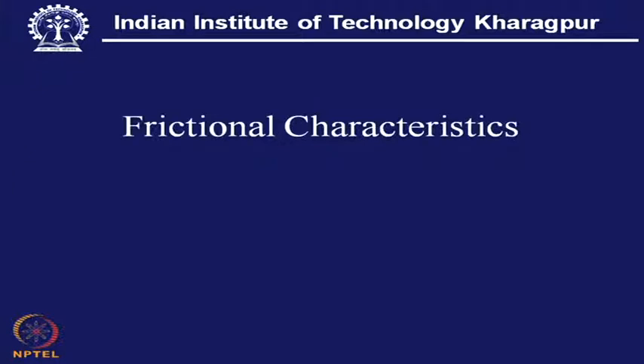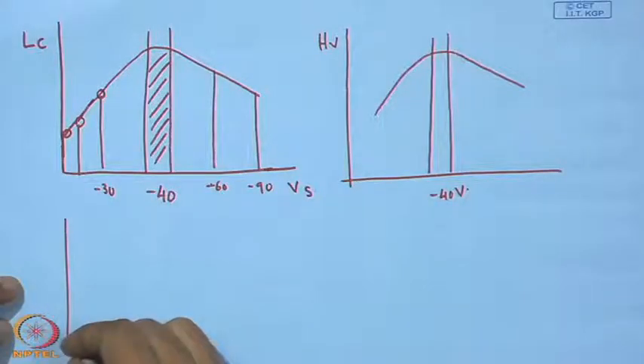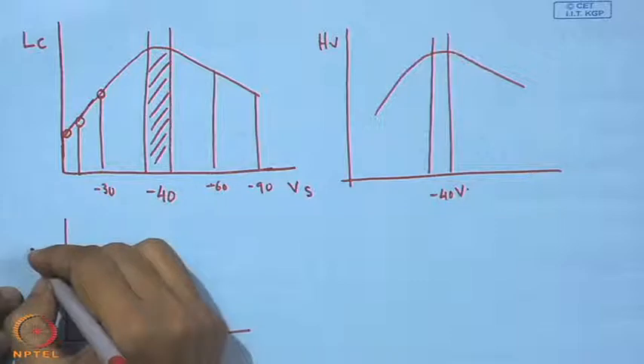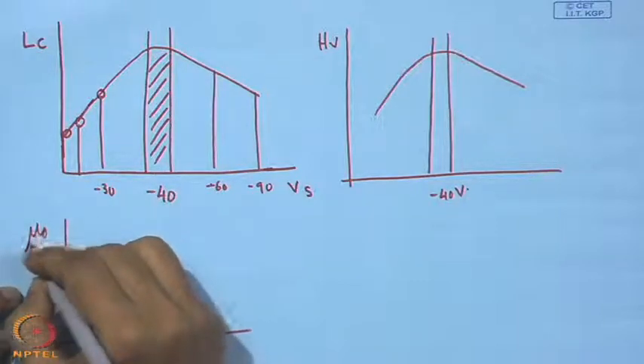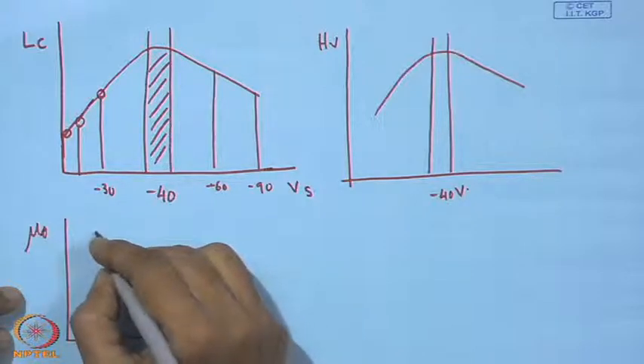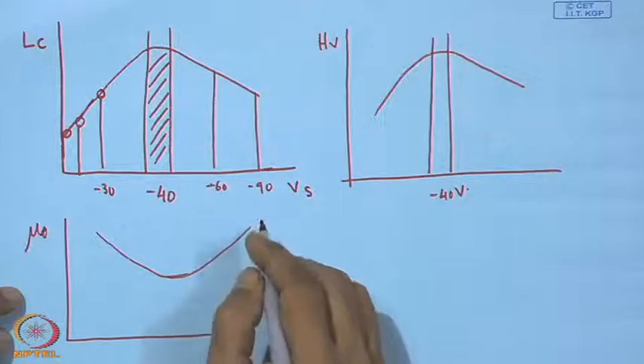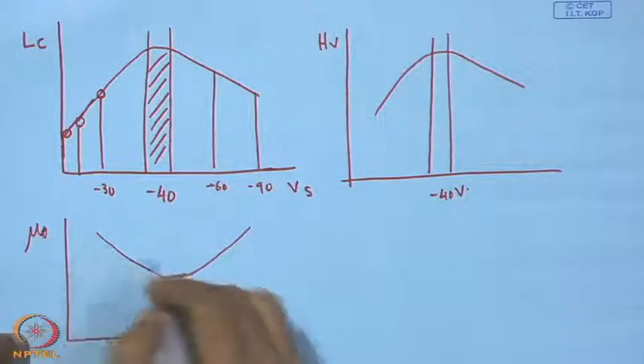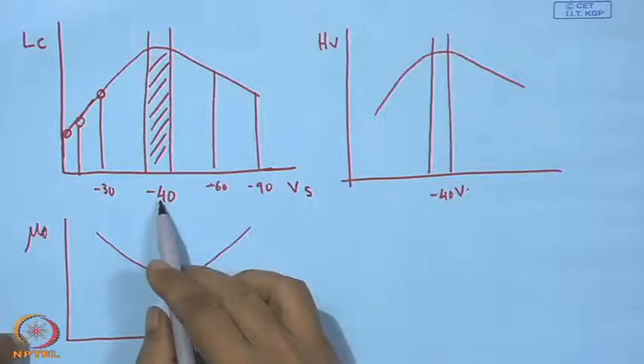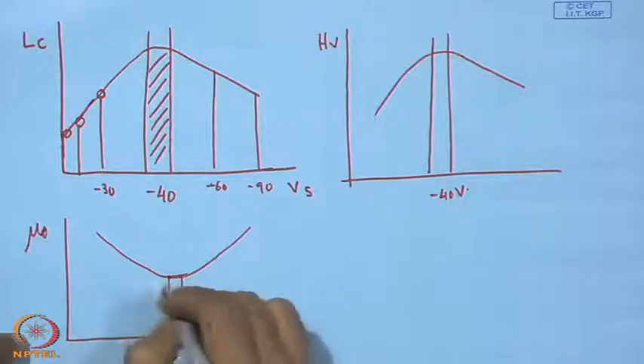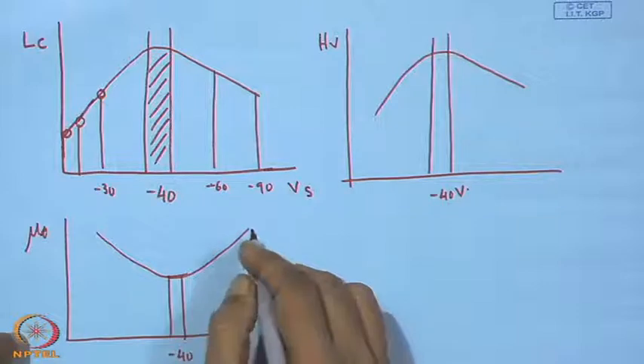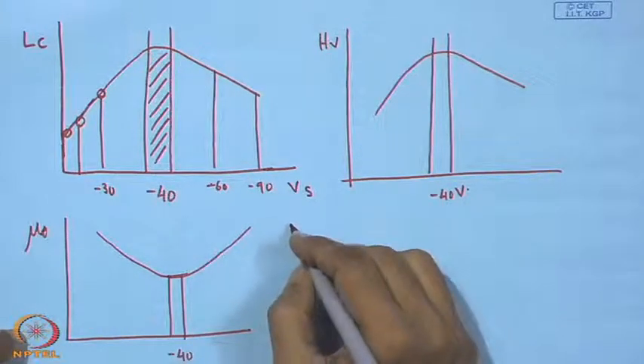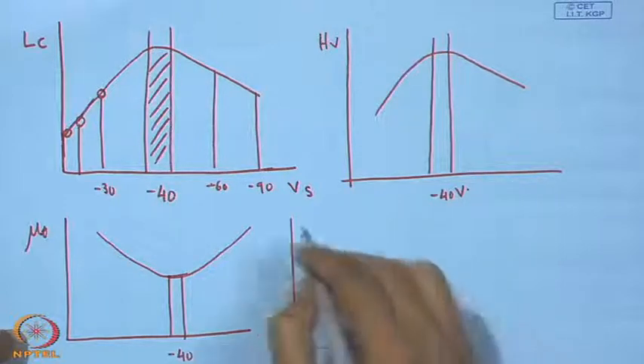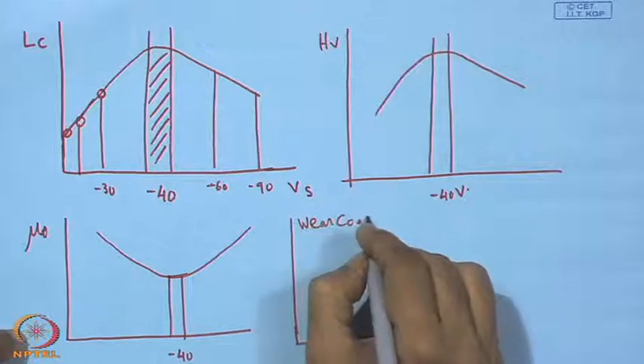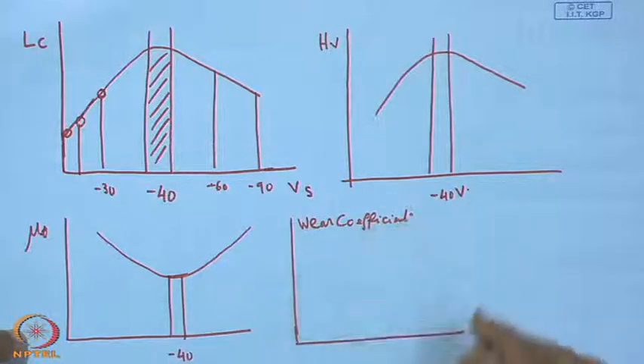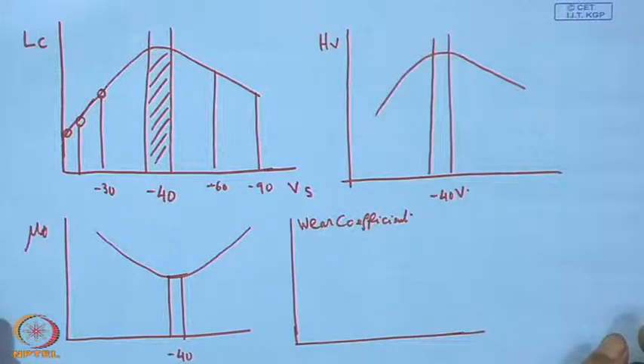Frictional characteristics. Now, with this also, what we have seen is that the coefficient of friction is lowest in between here. So, this is actually given by a particular morphology of the coating, which we could get around this value, and on the two sides the coefficient of friction is rather high, and this will also lead to another graph which is called wear coefficient. So, this is a measure of wear on the ball or also on the disc.